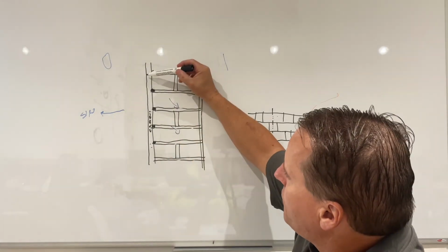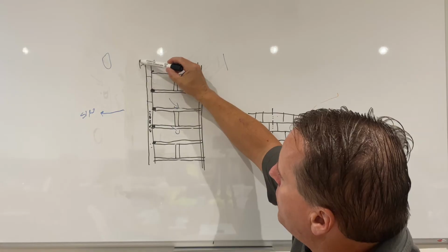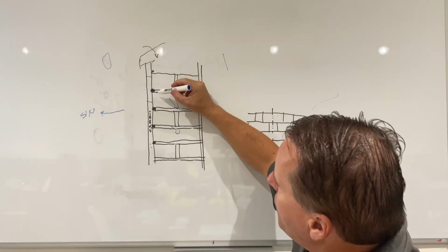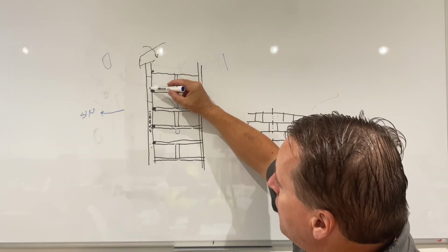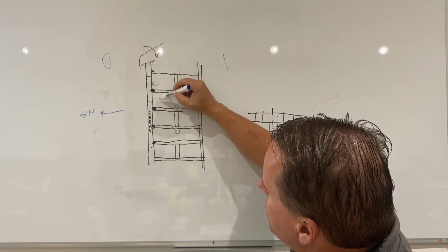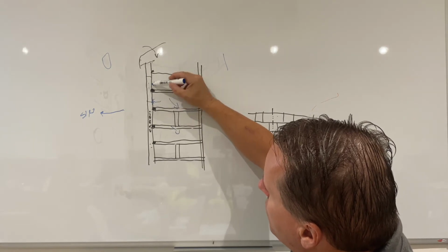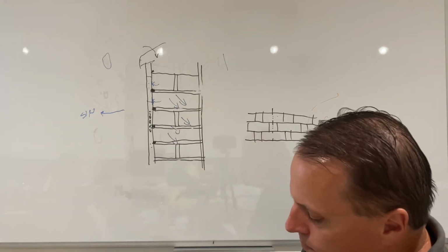Well, what it does, wherever you've got little hairline cracks in the render, or if you've got a window sill up there, you'll get water coming around the sides of that. Water can still get into the wall construction, but not only have you then got this mortar pointing here, and it doesn't matter if that could be lime, because you've got this impervious coating on the outside, no moisture vapor can now get out because it's formed a barrier.